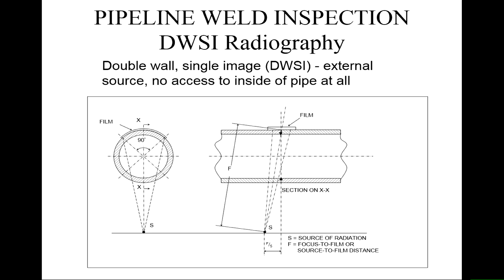And if you offset that, you can make it more likely that you'll separate the defects from the front end and the back end, in that they're spatially separated. Since we're only looking at a weld which goes round in one circle here, we can spatially separate the weld from one side and the other side, so we can move the front end to one side and the back end to the other side. This is only really applicable when you have no access to the inside of the pipe. So you've got options, depending on what sort of things you can actually do, given the pipe job that you're working on.